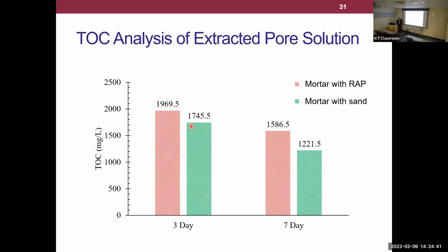Next thing we did is we used a very large die press, and we squeezed out all of the pore solution from the concrete. You just put it in a die and squeeze it all out. So that's our pore solution that we pulled out from the concrete and sent to the TOC analyzer. Red bars are mortars with RAP, green is mortar with sand. You'll see that even the mortar with sand still had organic compounds. That's probably because we have to use a fluoropolymer release compound in the die. Otherwise, it would never come back apart when we try to get our sample out. Picture like a Teflon spray. So of course, we're going to see some organic compounds in our control.